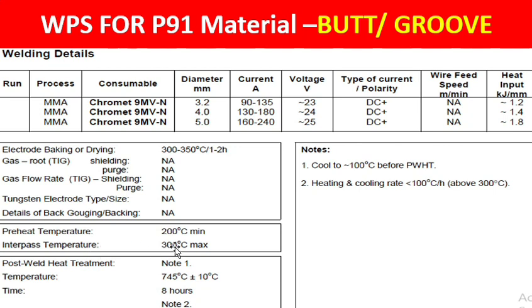Post-weld heat treatment is the same, 745 plus or minus 10. Time is 8 hours, not 2. Heating and cooling rate is the same, less than 100 degrees centigrade per hour above 300 degrees centigrade. So this is the post-weld heat treatment for this particular WPS: time is 8 hours, 745 degrees centigrade plus or minus 10.